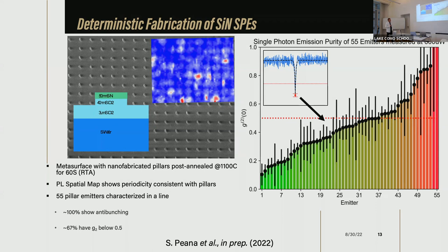Let me explain why. What we did, because at the end of the day, you don't want to have them randomly positioned. You want to prepare them in a deterministic fashion. So we made this array of silicon nitride pillars, which are sitting on a silicon dioxide substrate. And it turns out that obtaining single photon sources depends on the size of the pillar. The optimal one turns out to be around 100 nanometers or so. And when you do so, what happens? We absolutely arbitrarily chose 55 pillars in a row. And all of them actually show anti-bunching, meaning the correlation function is below one.